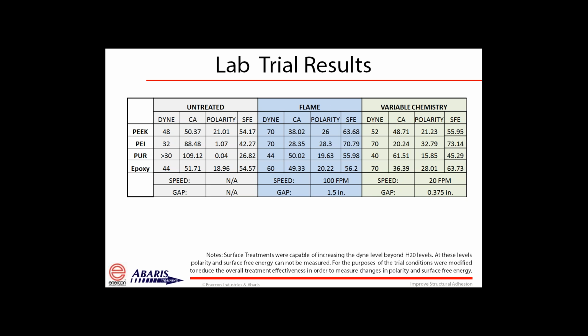We did the same thing with flame and variable chemistry, and you'll see here, I won't walk through all the results with you, but you'll see again, even at speeds of 100 feet per minute on flame, which tend to be pretty slow from a flame application, we do impact dyne, contact angle, and surface free energy pretty significantly on these advanced materials.